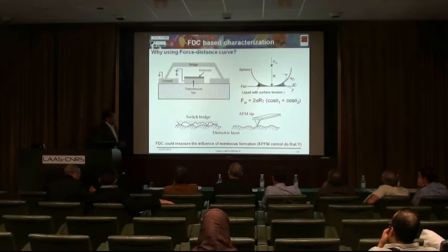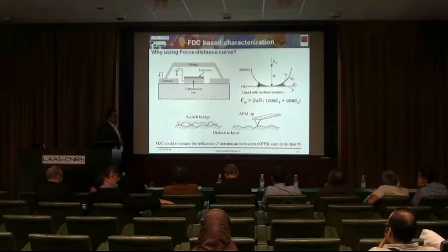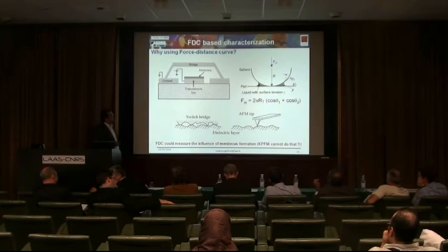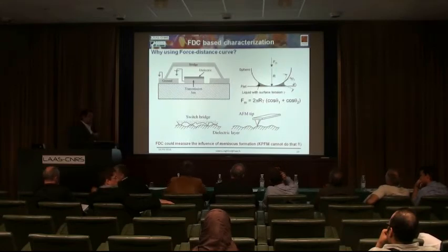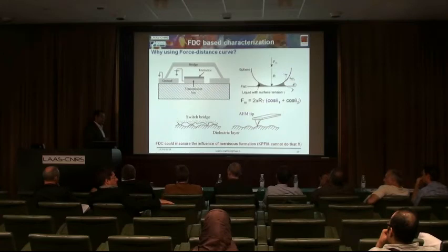The last part of the question regarding meniscus is, what you've seen: if the surface is hydrophilic, meaning the contact angle is less than 90 degrees for a given liquid, you form this concave-shaped menisci, which results in an intrinsic negative pressure, or intrinsic attractive force. So what sort of things would one do in general, let's forget about a switch for a second, with something that may be attractive? What would you do to get rid of it? I don't want to form a meniscus.